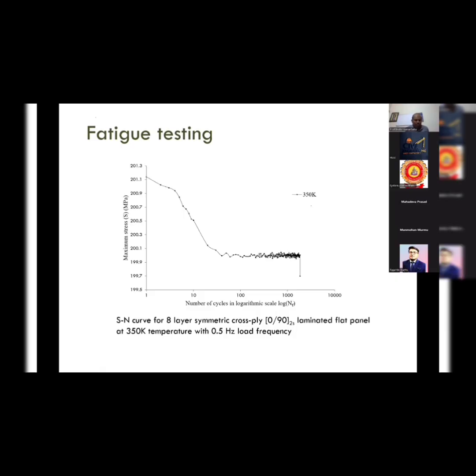One student has worked on fatigue testing of composite with nano alumina. This is a plate of composite with nano alumina. Actually this one is not nano alumina; we have done it with normal composite, the SN curve for an 8-layer symmetric cross-ply laminated flat panel at 350-degree temperature. This is for temperature only. So we have studied this one, and also done the SN curve with nano alumina as well.